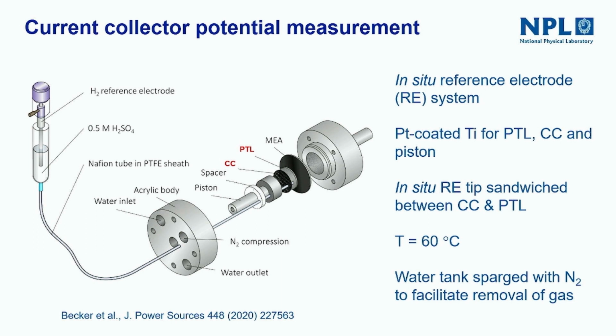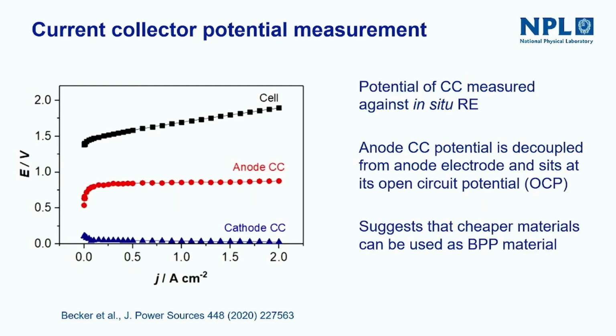And I guess the neat trick about this salt bridge is that it's a Nafion tube. So it's made of the same material as the membrane, that is proton conducting. So it's a solid proton conducting salt bridge with an external reference electrode. And that is just a really neat way of making a small hole. This is a 1 millimeter diameter tube, and you can terminate it anywhere and measure the local corrosion potential. So that's what we did.